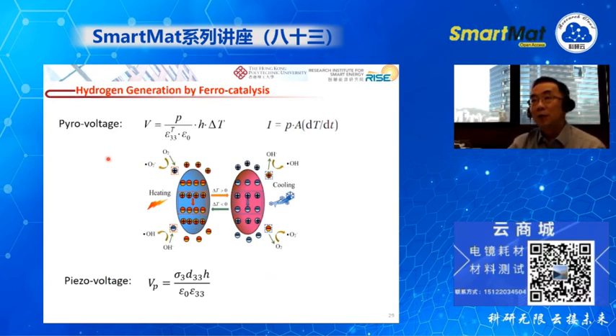We can also use pyroelectrics for the water splitting or the hydrogen generation. Remember, for pyroelectric material, the spontaneous polarization is responsive to the heat or the applied stress. So when you change the temperature, you will get a pyroelectric voltage. And similarly, if you apply a stress, you will also get a voltage.